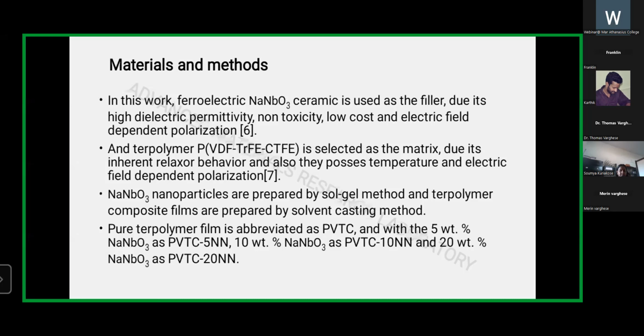The sodium niobate nanoparticles are synthesized using the sol gel method, and the composite films are prepared by the solvent casting method. Here the pure polymer is abbreviated as PVTC, and with the different loadings of sodium niobate, it is abbreviated as PVTC 5NN, PVTC 10NN, and PVTC 20NN.